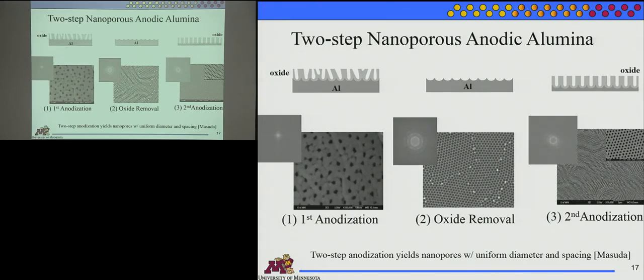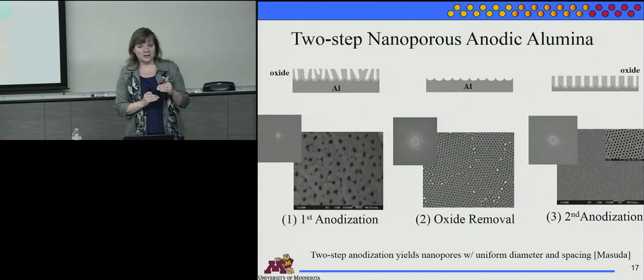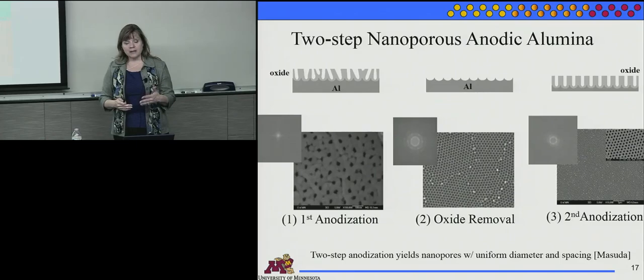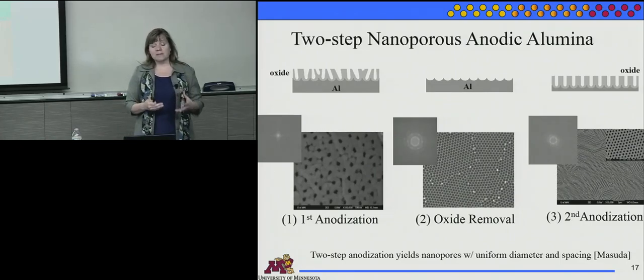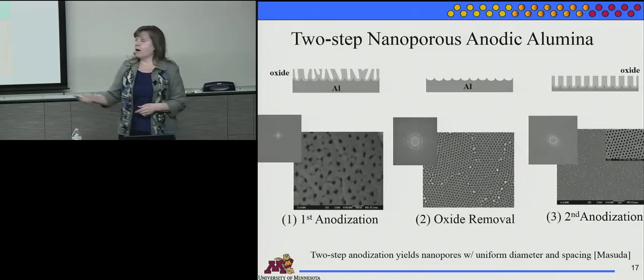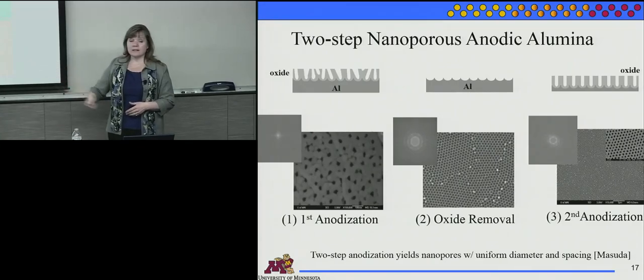And what happens here? Well, how long does that take? Well, the more time you have, the thicker the aluminum film that you have, or even a piece of aluminum foil, the more ordered your pores could be. But after even just minutes, they're not bad. Often there's papers that talk about 16 hours.